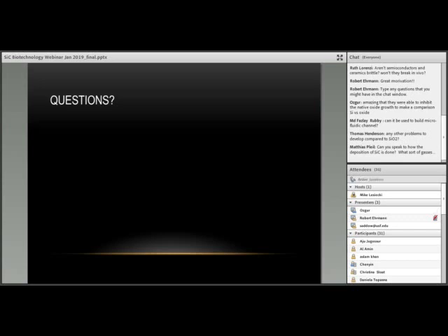That's a very good question, Ozgur. So we went through a lot of trouble to make sure that we reduce the oxide on the surface using HF, and then quickly immersed these samples into ethanol to prevent oxidation, and then straight to cell culture. So there may be a very thin native oxide, even for those silicon samples. Since we understand microelectronics, trying to control that, as you know, is difficult. So I would imagine there's a few monolayers of oxide on the silicon surface.